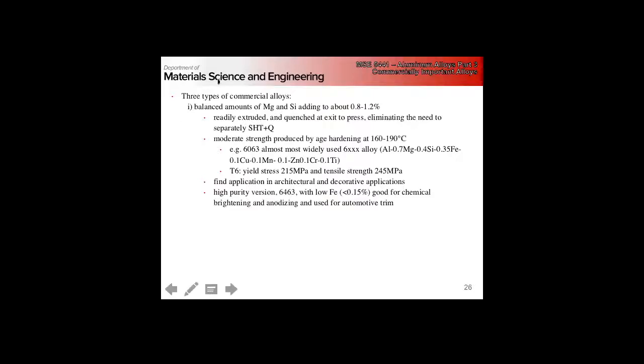We can eliminate the need for a separate solution heat treatment after, because of the extrusion processing step—the extrusion takes the place of the solution heat treatment. Then we quench at exit, since we're extruding at elevated temperatures, and then we age these at between 160 and 190°C.